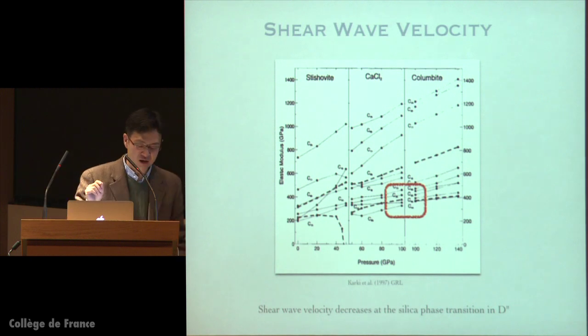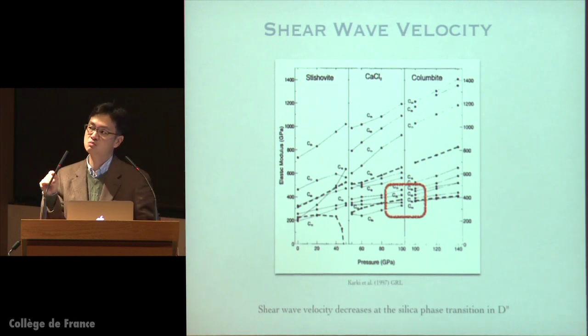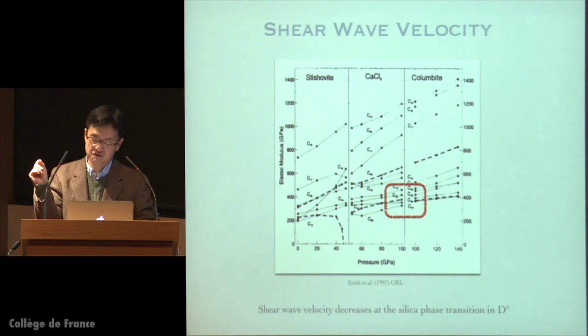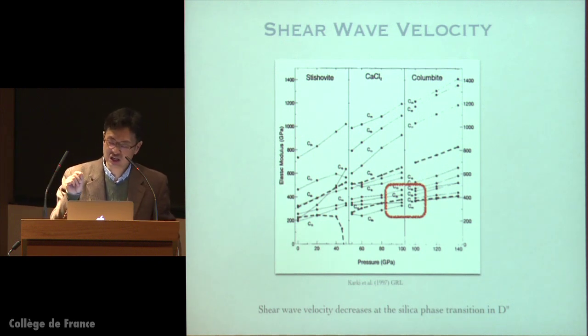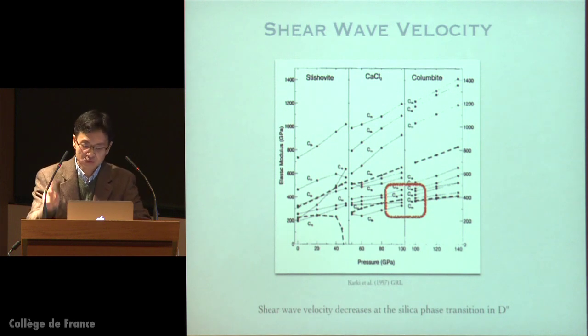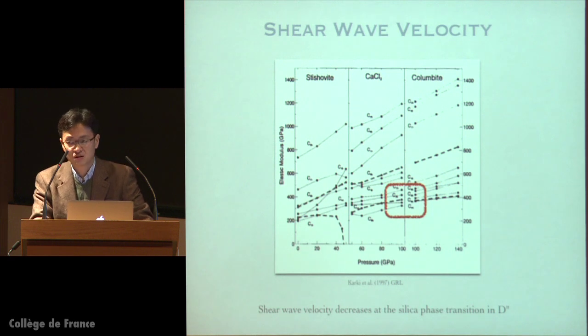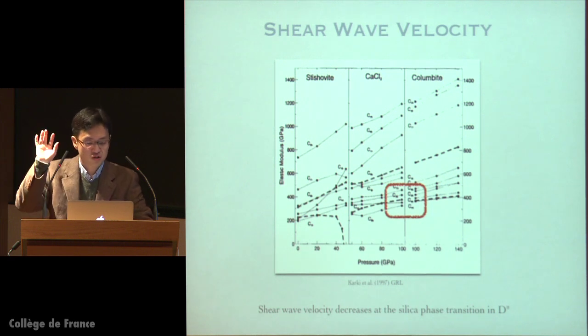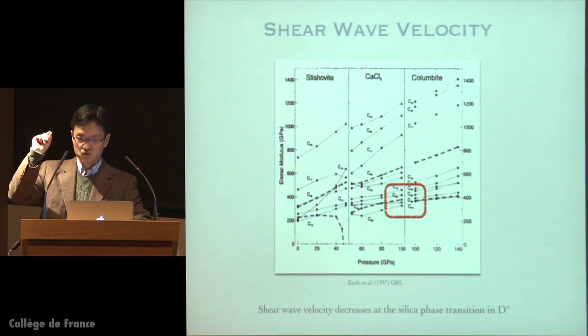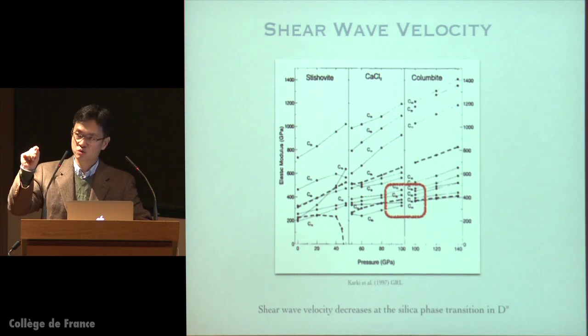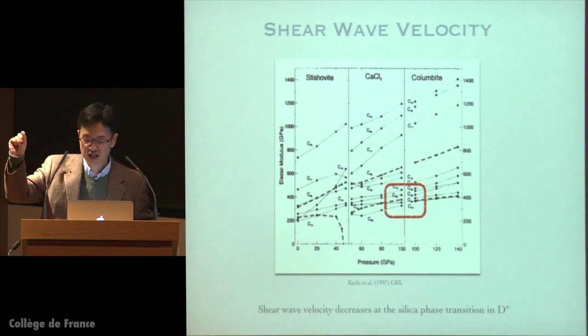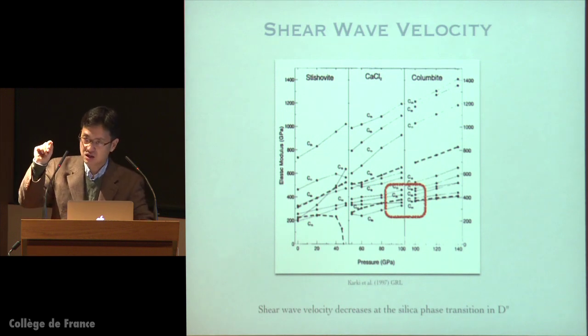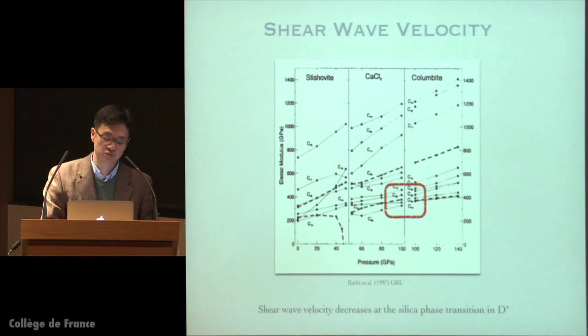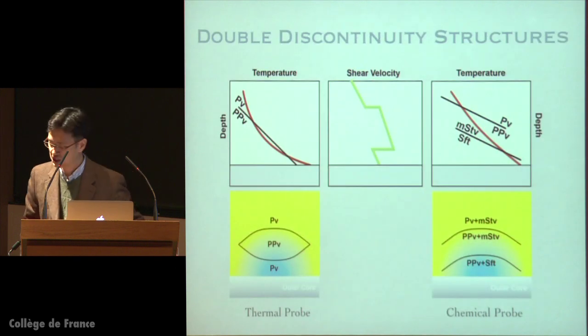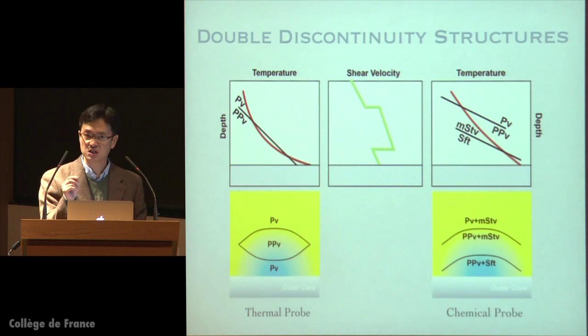Although I don't show you the data, we found that the bulk sound speed shouldn't change much across this silica phase transformation. But there's an interesting theoretical estimate. There are actually two, basically saying that shear velocity should decrease across this boundary rather than increase. Just to remind you, for the post-perovskite transformation, we expect that the shear wave velocity increases about 2 to 3%. In this case, they estimated that it'll decrease by 1 or 2%. So that gives us a pretty interesting case to interpret some of the observations that have been made.